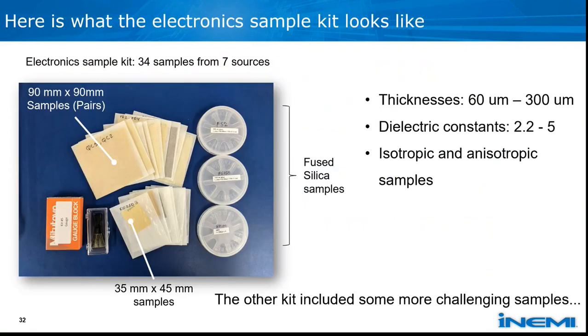Thank you. So the first sector of industry we really looked at was the electronics industry, which is really highly represented in this meeting. And so our samples from the electronics industry, we had 34 of them, and they came from 7 different companies. And they had a broad range of thicknesses and dielectric constants within what's reasonable for sort of typical substrate materials. So we had thicknesses ranging from about 60 microns to 300 microns, and dielectric constants from about 2 to 5. And these materials also added some anisotropic samples, which we did not see represented in the task 3 samples.